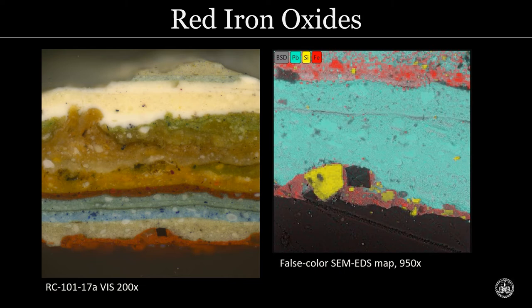So some of the other ways that I confirm red iron oxides is through this really neat technique called SEM EDS mapping. So in the image on the left here, you see a cross section from the Robert Carter house. This house was dated dendrochronologically, that means tree ring dating, to 1723. So we believe that this very, very first red-brown layer dates to that time. And it was such a bright, intense red that we got really excited because we thought it might be vermilion, which is a mercuric sulfide, which would have been much more expensive than red iron oxide and would have just told us a lot more about the person living in the house at the time.